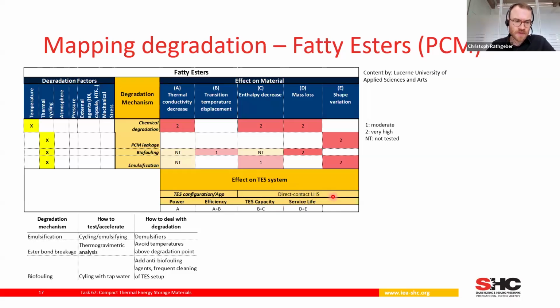In addition, there are some recommendations on how to test and accelerate the relevant degradation mechanisms and how to deal with degradation. So for the example of chemical degradation, that would be ester bond breakage, which can be tested with thermogravimetric analysis. And well, here it's quite obvious how to deal with that. Higher temperatures above the degradation point should be avoided.